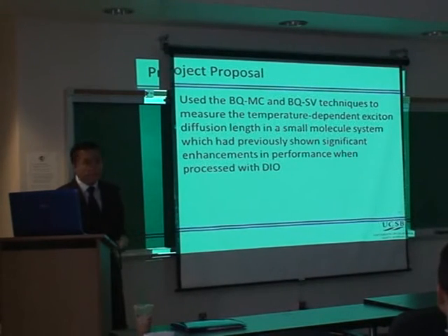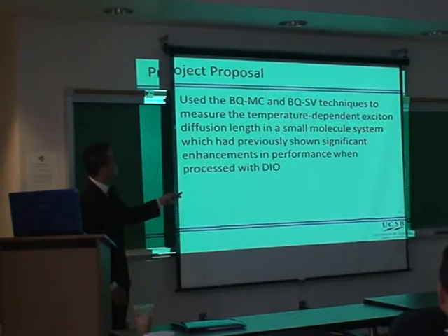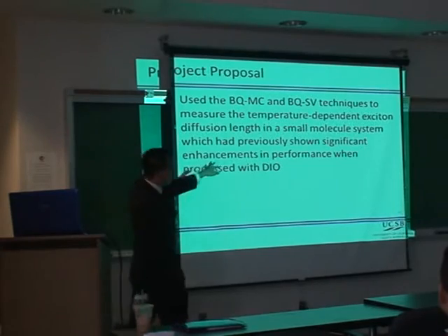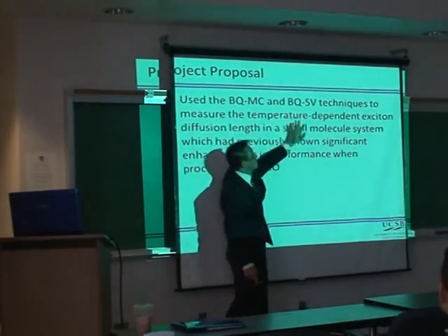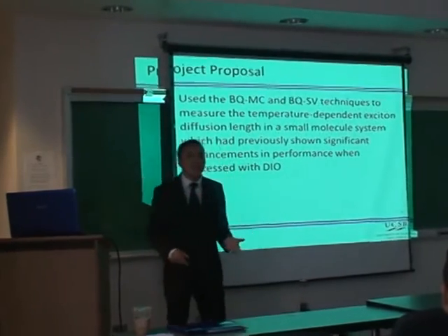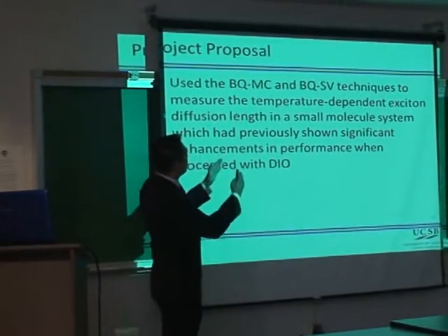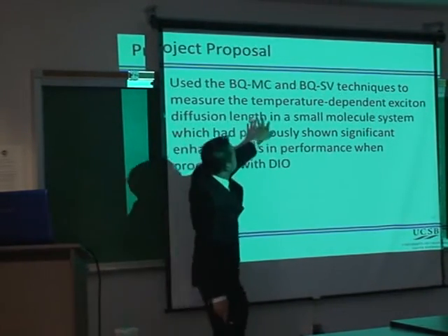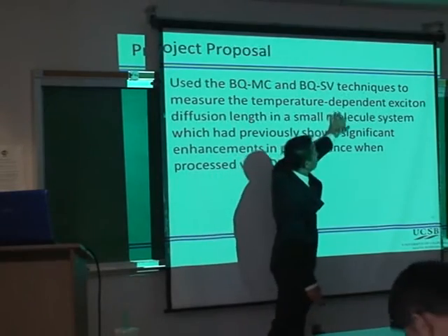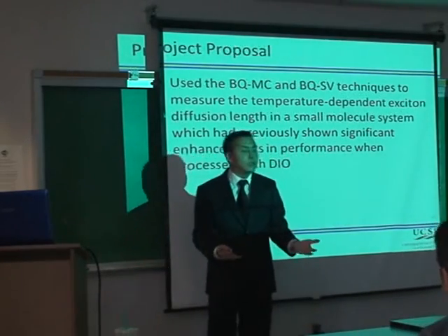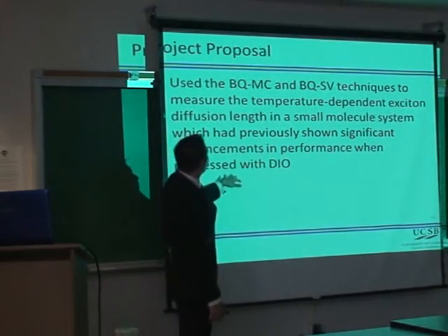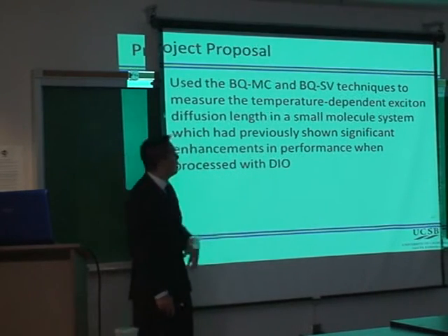And the project proposal was basically to use the bulk quenching method plus this bulk quenching Stern-Volmer method. And I didn't discuss this technique, but what's nice about this one is that you can actually calculate the exciton trap density in your film. So that's why we want to do those two in parallel. And we want to compare these two with temperature dependence, measure the exciton diffusion rate at different temperatures, and also with different processing conditions, with and without the DIO.